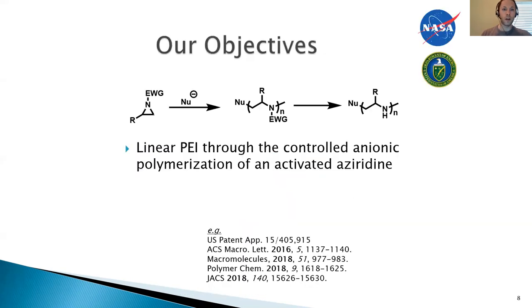Although these polymers are very powerful, it turns out they're really hard to make. These nitrogen-rich polymers don't have simple routes for controlled polymerizations. That's what we try and develop in the Ruppar group — we're very much interested in developing new synthetic approaches to make PEI-like polymers in a controlled fashion. By control, I mean that we can target specific molecular weights, and the molecular weight distribution of those polymer samples are fairly narrow.